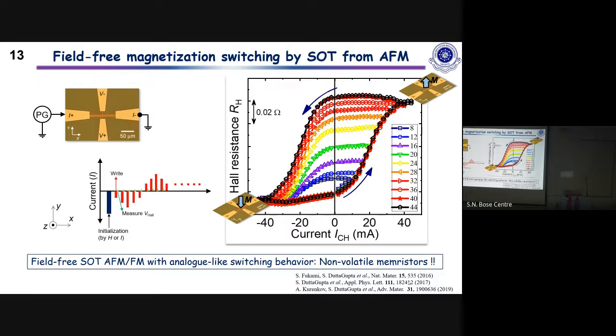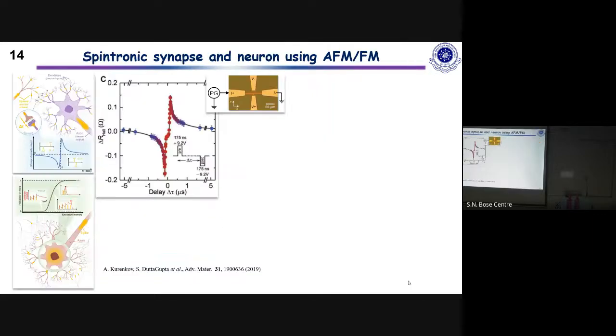Subsequently, we collaborated with ETH Zurich, and they did beamline experiments. They did XMCD on our samples, and they found out that these different resistive states are because of the switching of the different ferromagnetic domains that we have. And these different ferromagnetic domains arise because the underlying antiferromagnetic domain imprints its domain pattern on the metal. But that's a different study that we did.